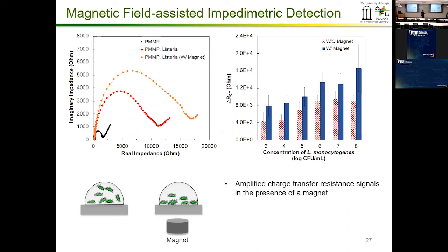So after we separate the samples with the help of a magnet, instead of introducing into the biosensor just by a regular gravity feed, we also wanted to aid the attachment with the help of a magnet, because the bacteria are already magnetized, so to speak. So when you put it with the magnet, you can see the impedance change. This is without the magnet. But when you put the magnet, it's a significant increase in the impedance change. It's actually better because you get a better signal. When you get a better signal, you can get a higher sensitivity for your measurements. Higher sensitivity means you're able to distinguish between 2 different concentrations very easily. You can see that with the help of a magnet, you're able to achieve higher signal for the charge transfer resistance.